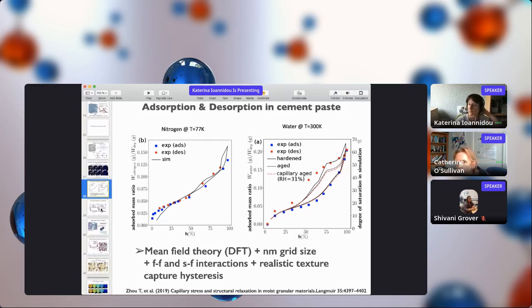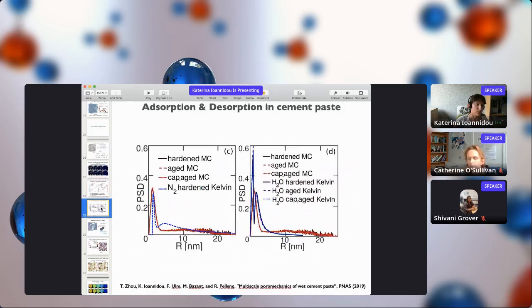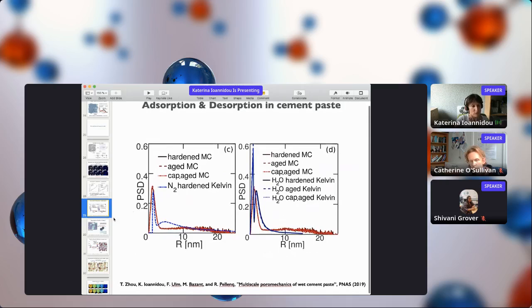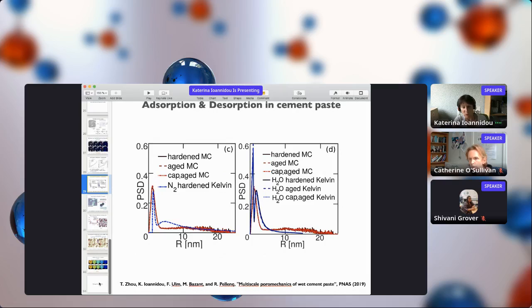Katerina, could you wrap up? Yes, I'll wrap up. So the next point is that if we compare pore size distribution computed from the simulations with topological characterization and from the adsorption-desorption curves, we see that we get the same gel pore peak and capillary tail when we use nitrogen, which is not the case for water. So, for example, that was a way to say that it's not appropriate to use water for such simulations. So I will wrap up here, and I'll be glad to take your questions. Thank you for your attention.